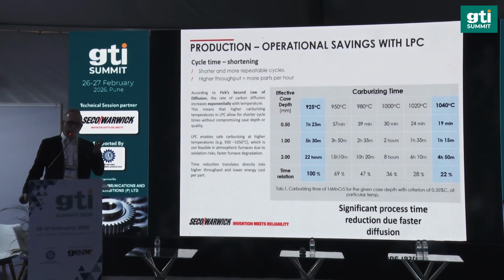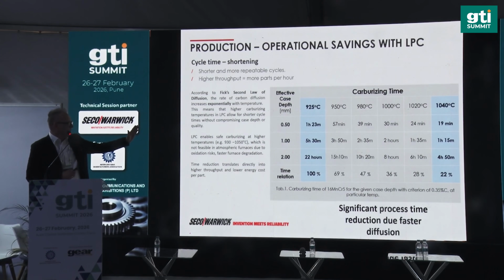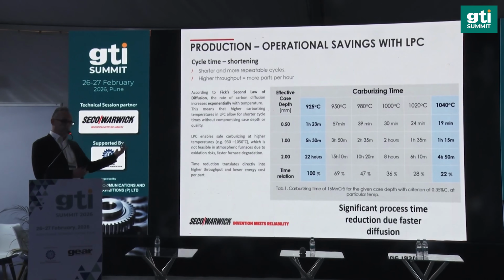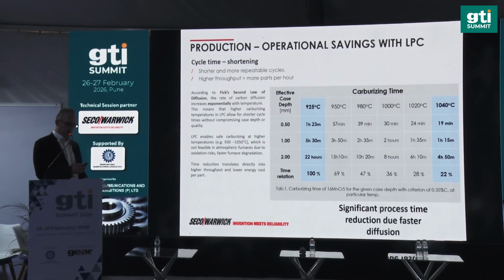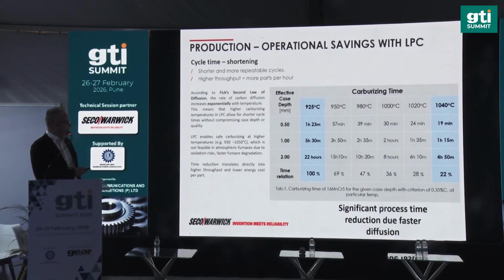I just mentioned raising the temperature. One of the benefits of that element is shortening the diffusion time, which means shortening the process. So if you can imagine raising the temperature from 925, which is typical for atmosphere carburizing, let us consider the 1 millimeter case depth, which would take 5.5 hours. If we would increase the temperature up to 980, we would decrease the overall time down to 2, 2.5 hours, which means almost a 50% decrease. That means you can either increase the throughput or not require as many furnaces as you would if you would run it with atmosphere carburizing, from an investment point of view.